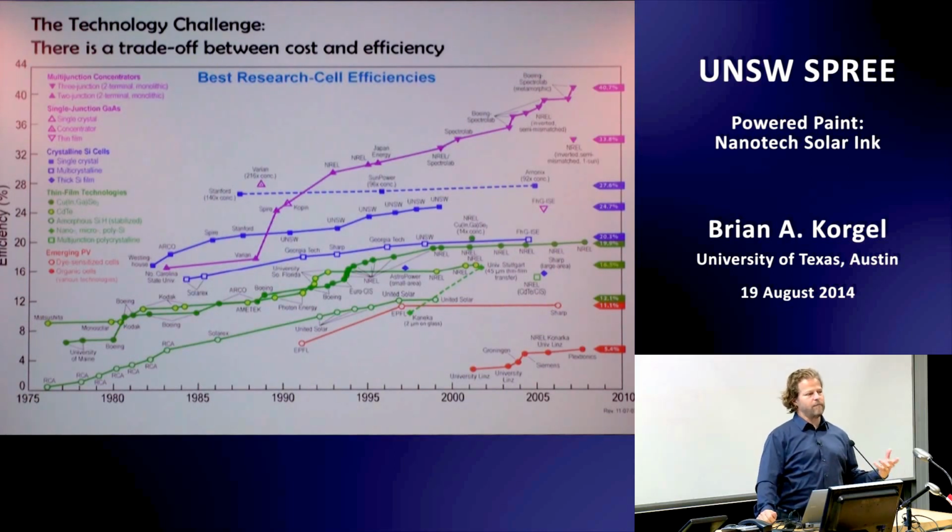Okay, so at the time, cadmium telluride had a real problem with stability. People eventually figured that out, sprinkle a little bit of copper at the back contact, and First Solar now works, but people didn't know that back in 2005. Silicon has some issues with absorption. It's an indirect bandgap semiconductor, so it's a pretty weak light absorber, even the quantum dots.